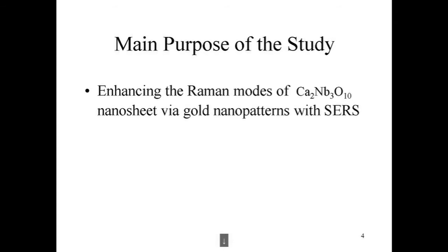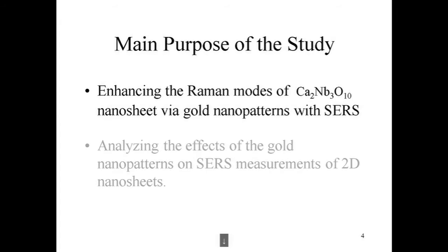This is supposed to be a surface-enhanced Raman spectroscopy application study. Normally, Raman modes of small inorganic particles cannot be analyzed since the Raman modes of the particles are significantly weak. The purpose of the study is to enhance Raman modes of the calcium niobium oxide nanosheet by using gold nanopatterns and analyzing the effect of the gold nanopatterns on surface-enhanced Raman spectroscopy source measurements of the 2D nanosheet.